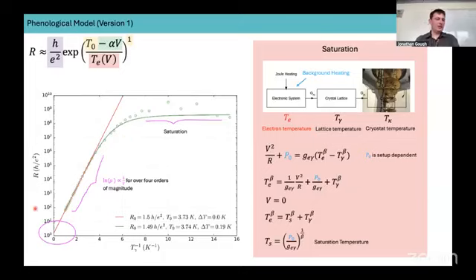These curves are calculated within the ohmic regime when the applied voltage is 0. But in experimental systems, you can also have other factors which influence the electron temperature, most notably high frequency noise or radiation. These are unwanted experimental effects that are typically very weak, that you wouldn't notice in, say, a good metal, which isn't very temperature dependent, however, they show up very strongly in these localized systems. So if you go through the heat balance equation and ignore the joule term, then you find that your electron temperature follows the lattice temperature, but then becomes limited by the saturation temperature.